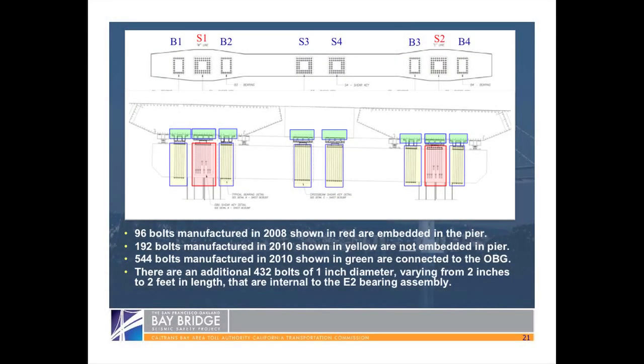The bolts that I'm now going to describe, the additional 432 bolts, are 1 inch in diameter. They're much smaller, and in fact they vary from 2 inches to 2 feet in length, and they are internal to the bearing assemblies, the Bs that you see on this sheet, B1, B2, B3, and B4. And so that comprises the totality of the bolts that are on the East Pier. It's about 1,200 of them. And again, manufactured in different batches, 2008, 2010, some of them of different sizes.